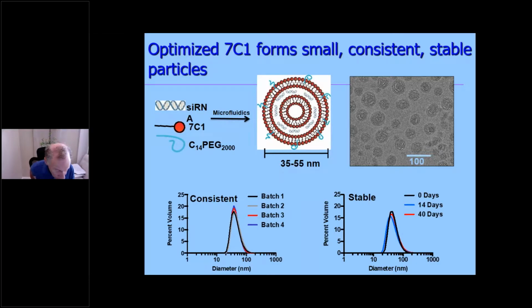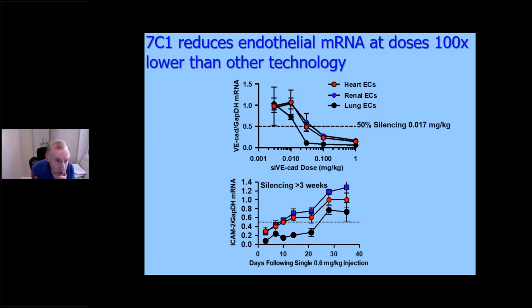And then if we go to the next slide, what we see is that when you made the lipid out of 7C1, it reduces endothelial cell mRNA at doses 100 times lower than any other technology. You'd get silencing for 3 weeks, and you can get 50% silencing with 0.017 mg per kg.